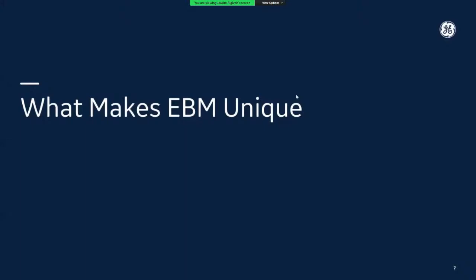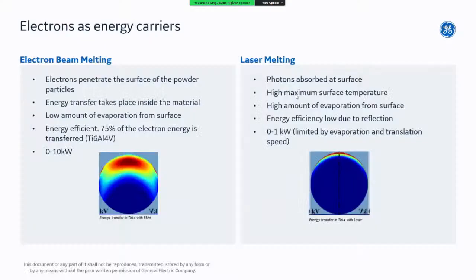What makes EBM unique as an additive manufacturing process? The major difference is using electrons as an energy carrier rather than laser photons. Electrons have a deeper penetration depth — as particles, they penetrate the surface and integrate with powder particles, depositing energy deeper into the powder compared to photons, which are typically absorbed only at the surface. Also, reflectivity is not an issue with electron beams since energy transfer occurs deeper in the material rather than at the surface.